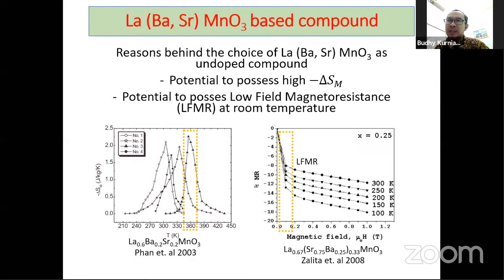So our sample is based on LBSMO, lanthanum, barium, strontium, manganese oxide. If we look at the figure, minus delta SM, or minus delta entropy, for the LBSMO, we have the highest value of minus delta entropy of about 2.3 for the minus delta SM.